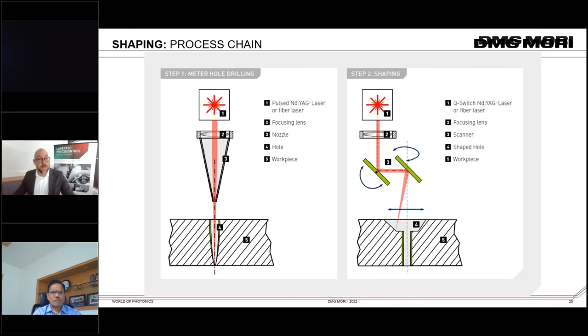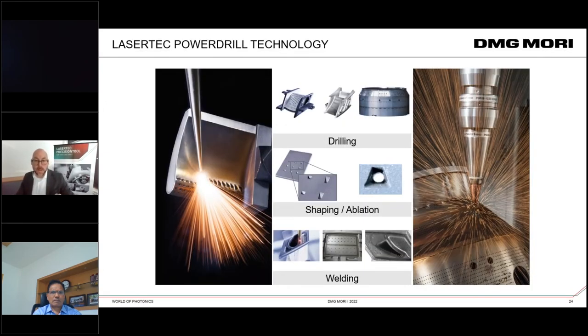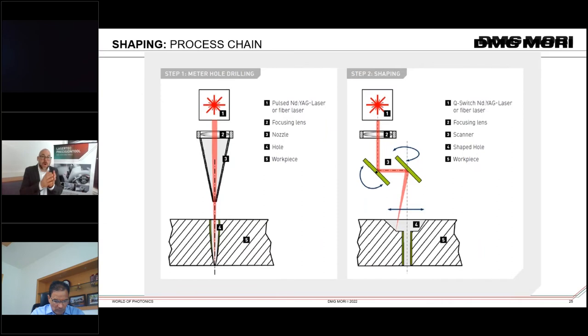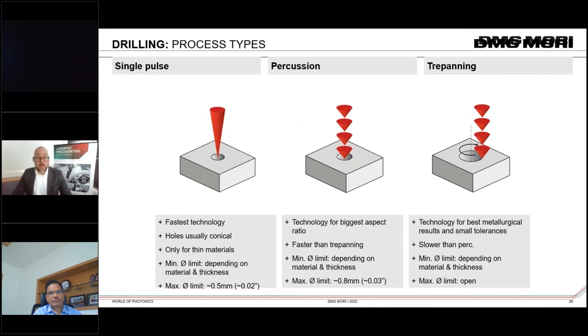Here we can see the process chain for shaping. Remember, shaping is, I go one slide back, to put around the cylindrical drill hole that shape hole geometry around, in order to force the air to go through that hole diameter. And the process is like this, that we of course always start with machining a center drill hole on the left hand side. This is what you can see. And if we go to the right hand side, step two is then putting the shape hole geometry around. And here, actually, we are using the same technology like we are using for our shape machines. So we have a scanner, and that scanner is directing the laser beam to the workpiece in order to generate an ablation, a layer per layer ablation. And then at the end of the day, we have this beautiful shaped hole geometry.